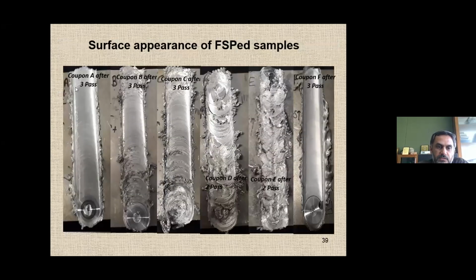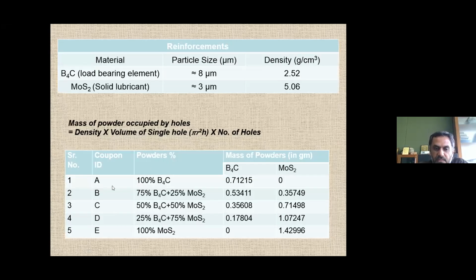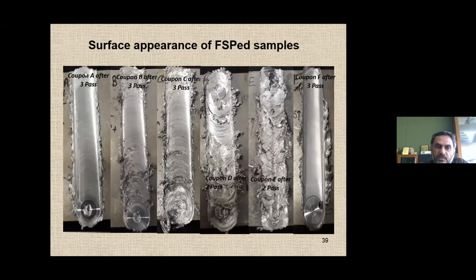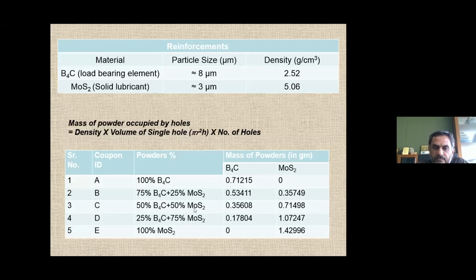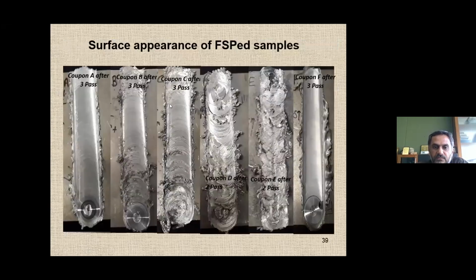You see, this is your 3 passes, right? A coupon, B, C, D. Your A was the 100% B4C. B, C. Then, as you are approaching, because your MoS2 percentage is increasing, you see here only 100% B4C, while here you see 100% MoS2. You see, because MoS2 is a dry lubricant, now it is acting as a lubricant. Now beyond 50%, you see here, this C is your 50-50. This is your C, which is 50-50.